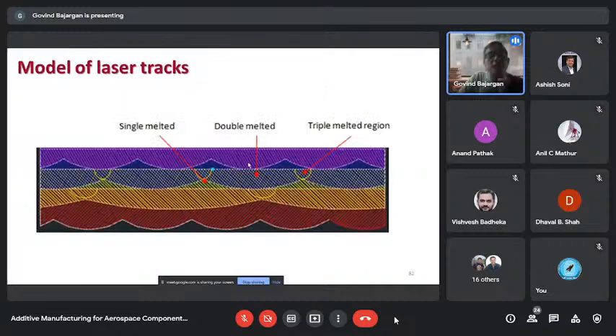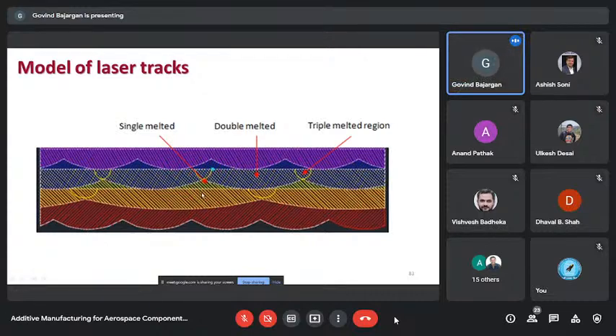We have done a similar simulation in CAD, wherein what we wanted to show is that when we are depositing a layer and the subsequent layer, the scanning angle is changed by 67 degrees. We know that the laser will melt at least 3 layers. So we find the zones which are melted 2 times, zones which are melted 3 times, and zones which are melted a single time. We wanted to know whether there is any change in the properties in such zones. So we did some hardness checks and found that hardness is almost in the same range, with not much change. And microstructurally, we didn't find too much variation. So it gives a fairly uniform microstructure.